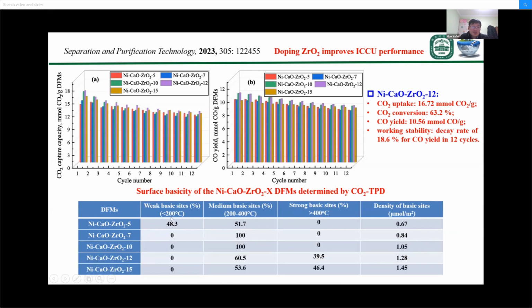Also, we have adopted the strategy of metal oxide doping to further improve the ICCU performance of calcium DFMs. We found that the doping has improved the density of the basic sites. With the increase of the doping content, the ratio of the strong basic sites has improved, which means that the basic sites have been transformed from weak basic sites to strong basic sites. These have further improved its CO2 uptake. We also found that the doping has increased the oxygen vacancies in the DFMs.